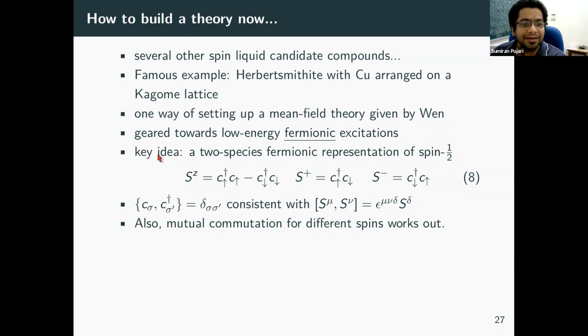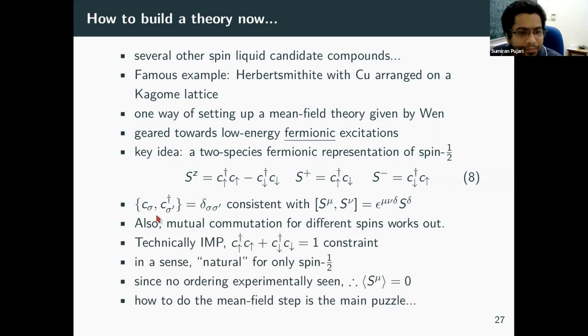And so the key idea here is actually a different fermionic representation of the spin half, which is a two-species fermionic representation. So instead of using the original spin operators, you use these fermionic operators, but there are two species, say up species and down species. And this is a mapping. And it turns out that the fermion anti-commutation algebra of these fermions is consistent with the spin algebra. And you can do more work and show that mutual commutation, because two distinct spins have to commute, is also consistent with fermion anti-commutation.